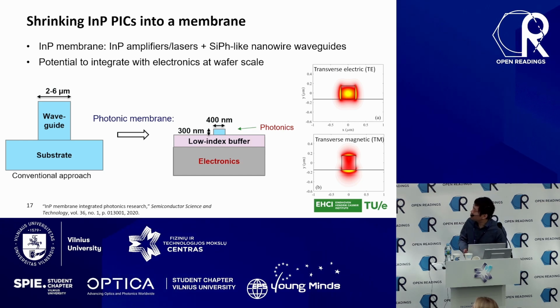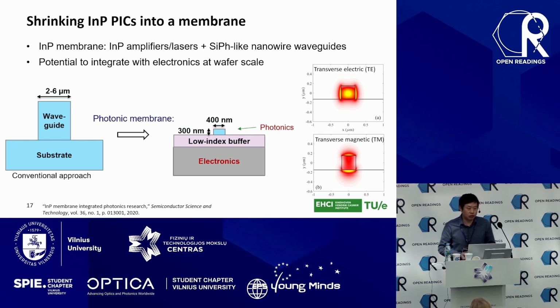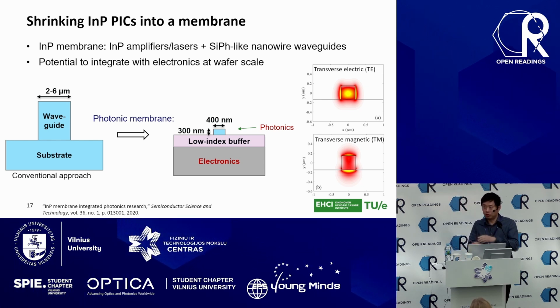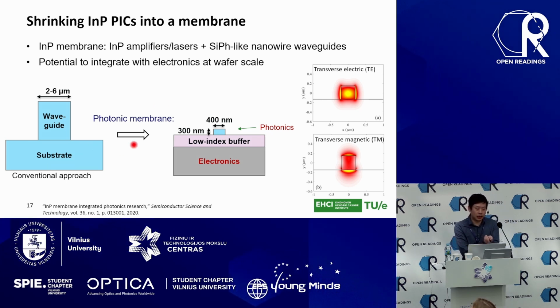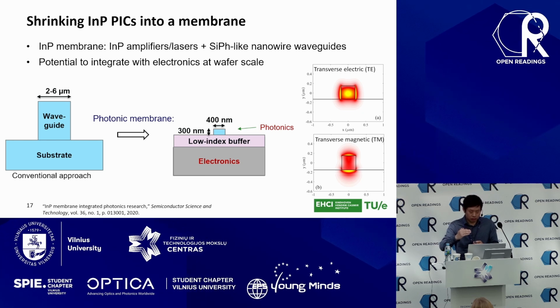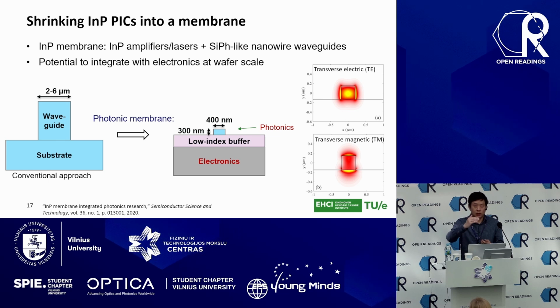So the choice of technology we use is to try to shrink the indium phosphide technology into a much smaller form factor. If you see on the left side, this is an illustration of a conventional indium phosphide laser structure or waveguide structure, where you grow your entire diode or waveguide structure on an indium phosphide substrate. Because you are creating a relatively weak optical confinement, because the index contrast is very, very small, it ends up